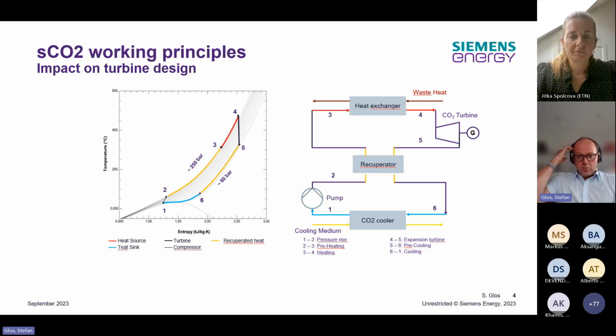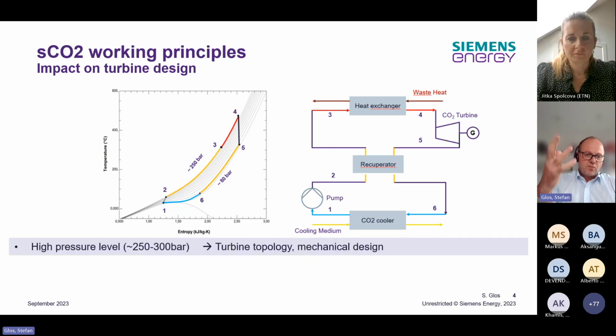Looking at the working principles of an sCO2 cycle, we see here a simple example of a recuperated cycle, in this case for a waste heat recovery application, and the process here on the left-hand side in the TS diagram. From that, we can already derive some basic requirements and challenges. The first one is for sure the high pressure level in sCO2 cycles. At the inlet of the turbine, we are speaking about pressure levels of 250 to 300 bar roughly. Therefore, you need a mechanical design of the machine which is really suitable for that.